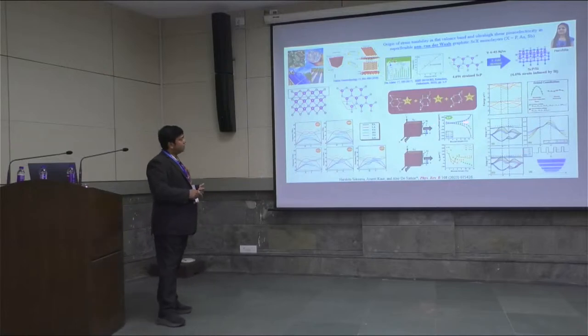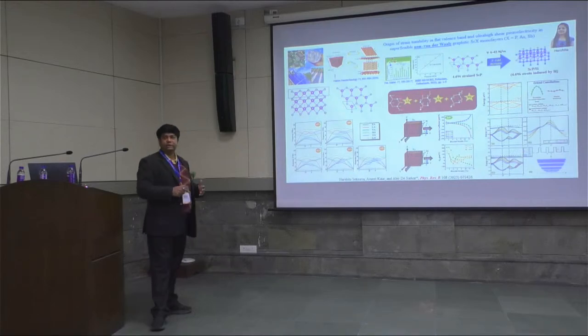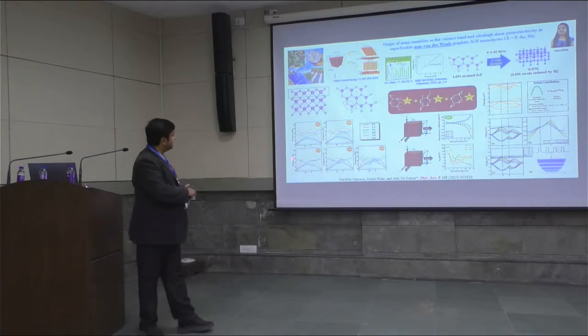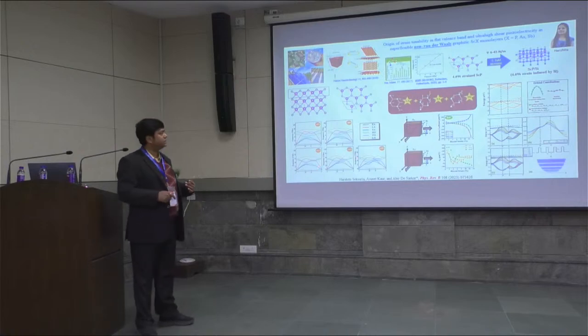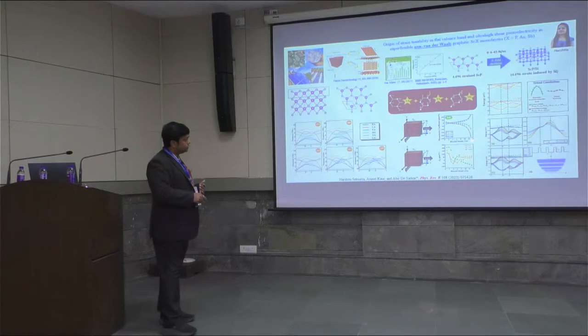Right? And so under the application of biaxial strain, we find that there is a complex mixing of these three phonon modes. They are most sensitive to the application of strain. The other phonon modes are relatively insensitive to the application of strain. And that is what is understood to enhance the shear piezoelectric coefficient in these monolayers.